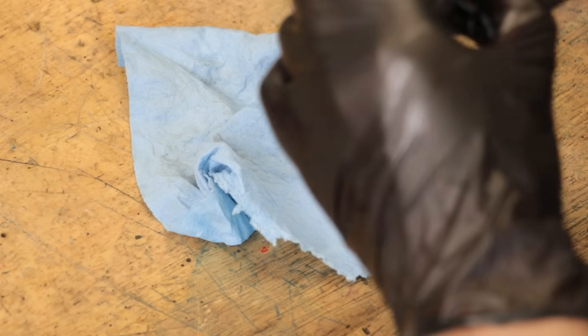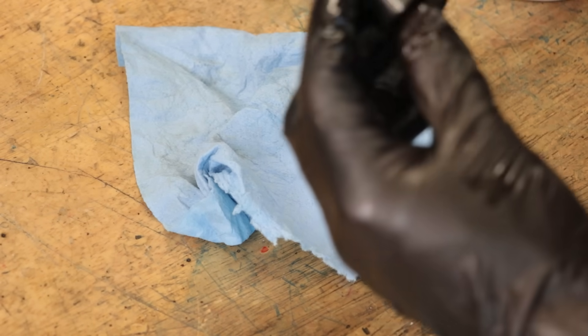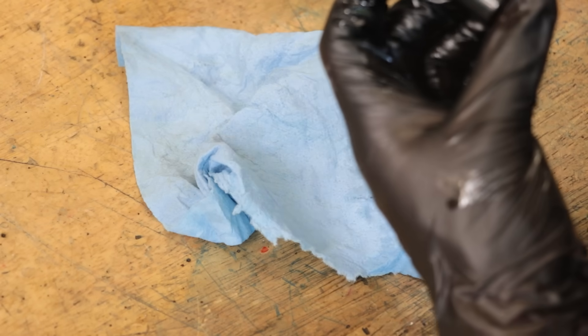The important thing is to leave it covered in oil for a few hours. Some people do it overnight, some for 24 hours. I normally just leave it overnight and then brush it off the next morning. As I understand it, the black coating is slightly porous and able to suck up some of the oil and retain it, and that's what gives it its rust protection.